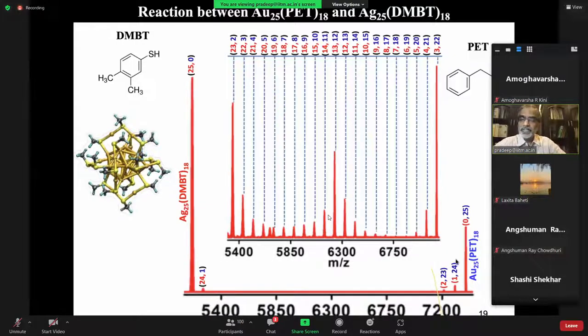And if you mix this, these peaks come up and we know what these peaks are. But if you mix this, you also see, and expand these regions, you see that there are many other peaks. And a whole lot of exchanges happen. And somehow some of these intensities are far more than other intensities. It appeared that this is because of an entropic contribution. Earlier I was talking to you about enthalpic contribution, and now greater entropic contributions are giving you these peaks.